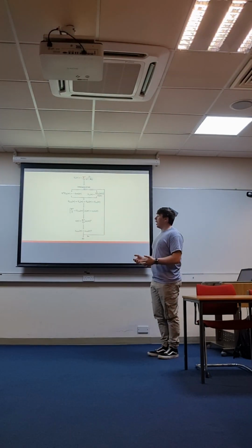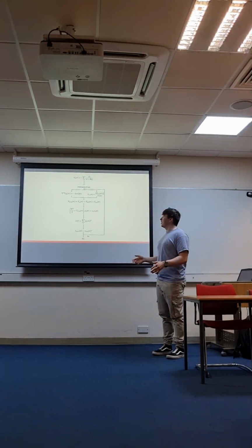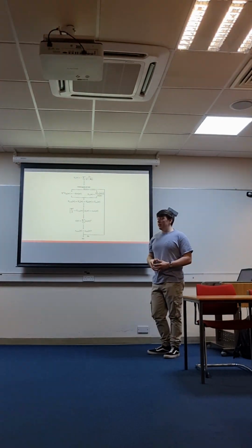So, let's put this all together in a DFT flowchart. We need to start this by having a nuclear potential. And we get this by specifying nuclear coordinates given by the big bold R. These are usually obtained through crystallography data. However, what one can do is vary the sites of the nuclear positions and find the energy of the system. Plotting the energies of the system, we can find which is the minimum, and this will be the structure of our material. So, it's then standard to have an initial guess of the electron density, which is usually done by adding up all of the individual isolated atoms' electron densities.